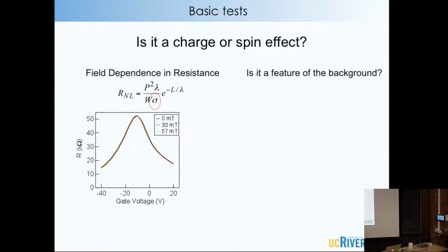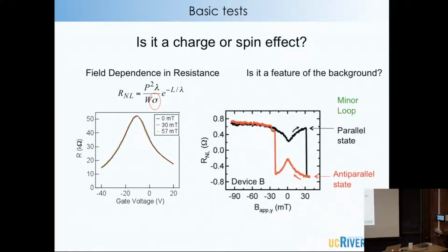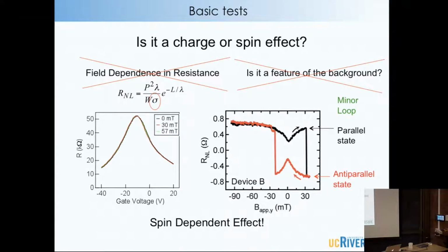The other thing is, is it a feature of the background? I didn't mention, but there's always some constant background that we subtract off. So is it possible that it's from some weird thing in the background? The way that you deal with that is you do what's called a minor loop. You come in here, you go through the dip, and then from the parallel state, you go to the anti-parallel state. And instead of completing the hysteresis loop, you just flip it around. If the dip becomes a peak, then you know it's from spin. If the dip stays a dip, you know it's from background. So it's showing that it's really from spin. So we know it's a spin-dependent effect, and we're very happy about that.